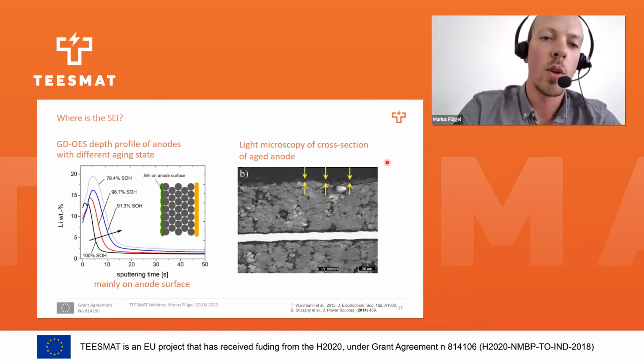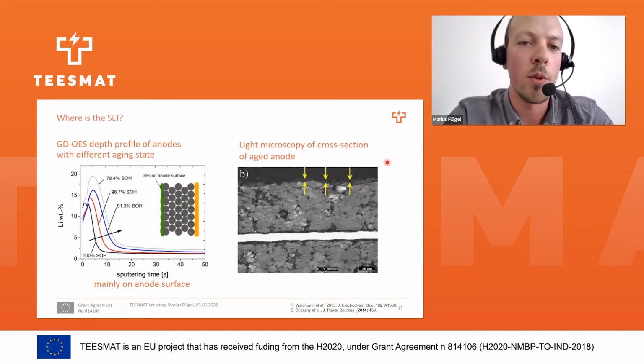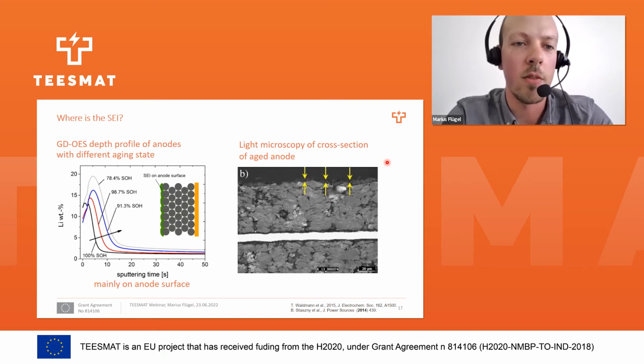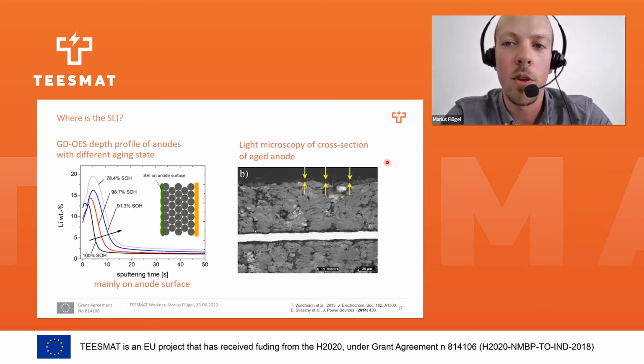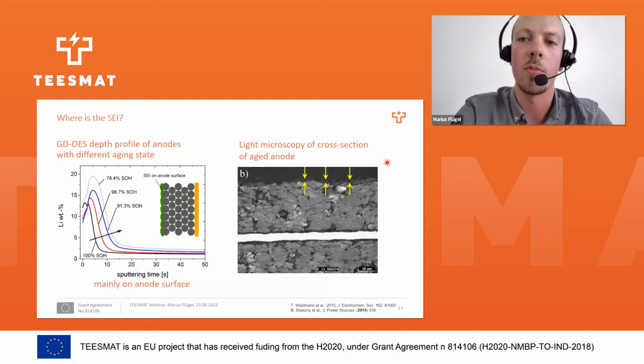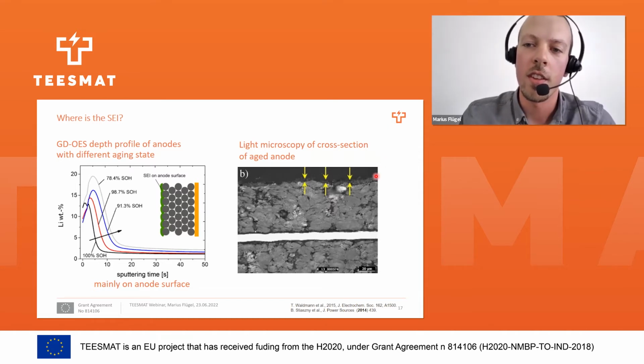With GD-OES, we could observe that lithium was mostly found at the anode surface, where there's a heavy SEI formation, which could also be observed with a light microscopy of the cross-section here.